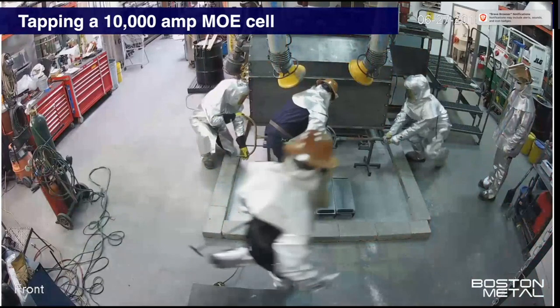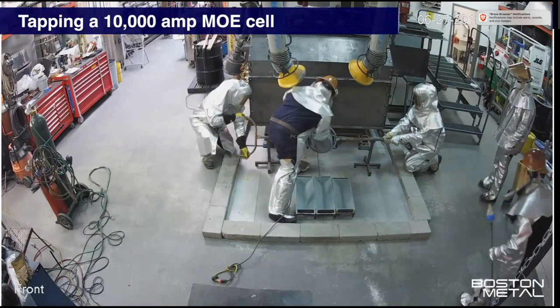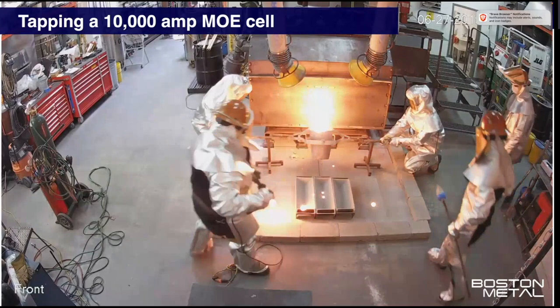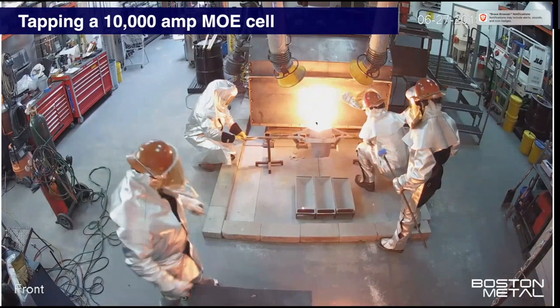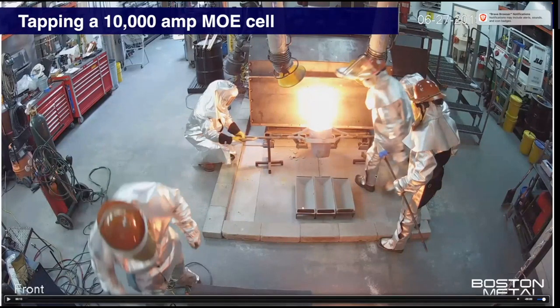So you will see they're about to open the cell. And now this is liquid iron at about 1600 degrees Celsius. And they're going to pour it into these molds down here, and then eventually close the cell and then let it go. So that's where the company is now, and they're about to raise new money with the intention of building cells on the order of over 100,000 amperes. And I think if you compare it to aluminium, once you get up over 100,000 amperes, people will start respecting you, that you really are at the industrial scale.